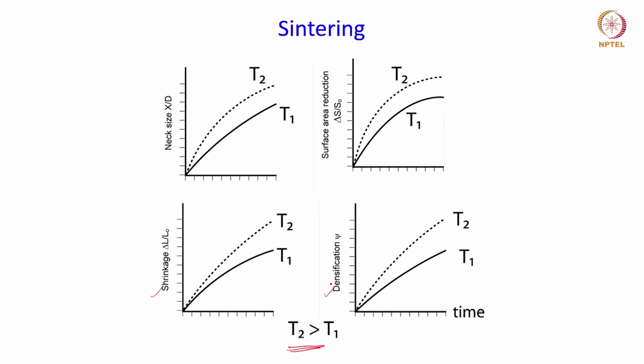Okay, so here you can see that as the temperature is increased, the densification is also increased, because all these parameters which define densification increase with increasing temperature, because as I said, the processes which lead to pore closure are all thermally activated processes, and therefore an increase in the temperature will lead to a higher densification. So when you talk about the sintering process as such, the two important parameters are the temperature and the time.